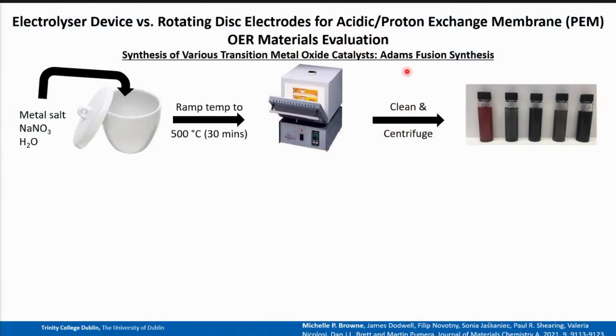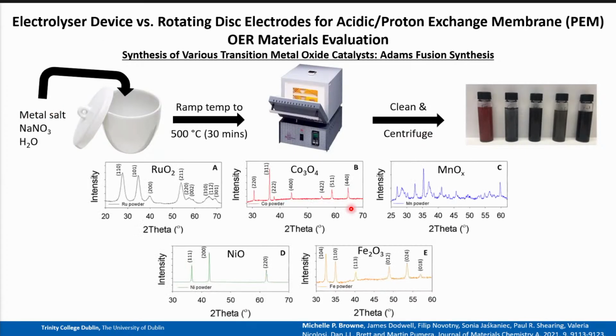So to do this work, essentially, I made 5 different catalysts through the Adams fusion synthesis method. So this is a very simple method. You just get metal salts with sodium nitrate and water into a muffle furnace at 500 degrees for 30 minutes. You clean and you centrifuge your materials, and then you have your catalysts. So I altered the metal salts 5 different times to make 5 different transition metal oxides. And these are the 5 transition metal oxides that I use for this study.